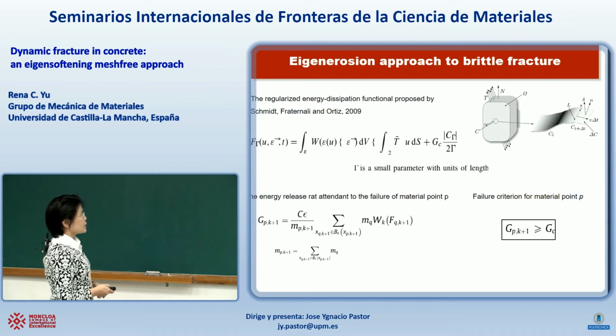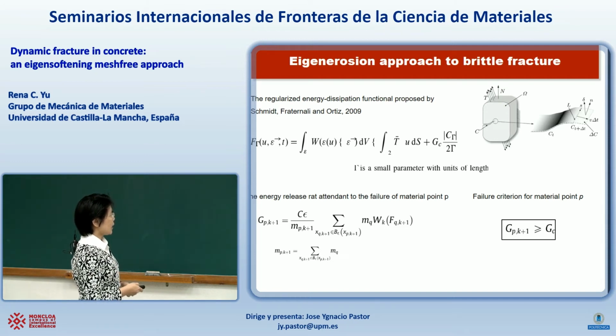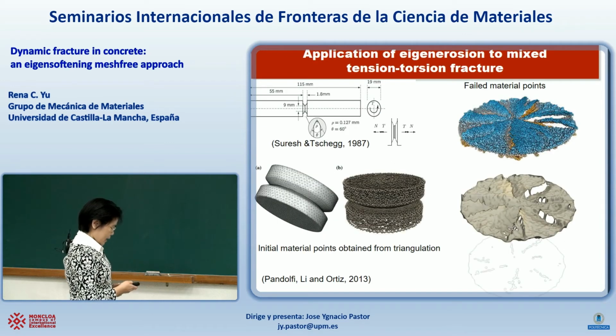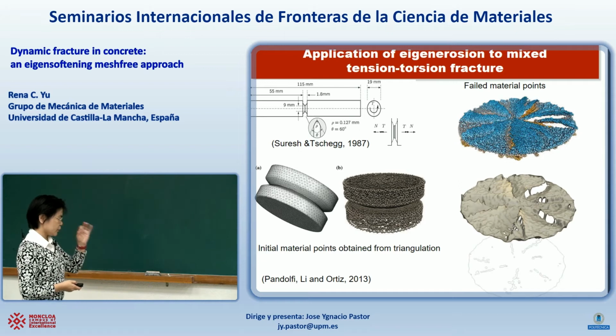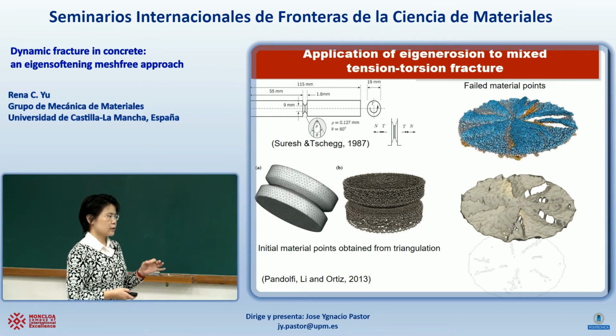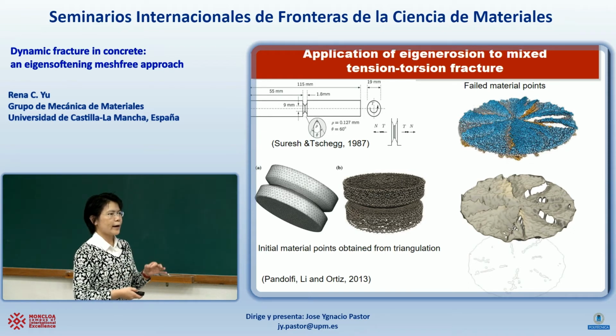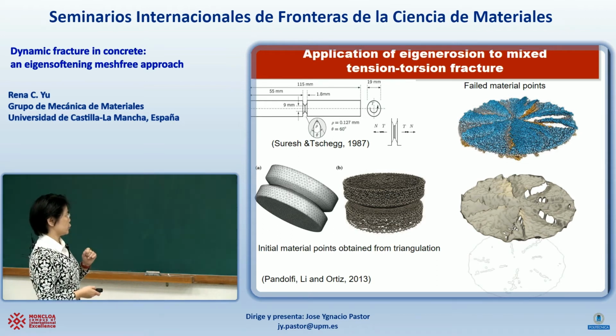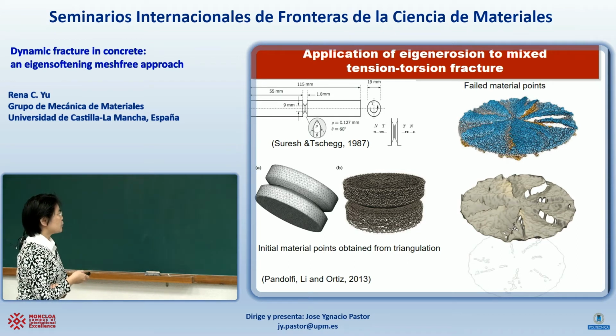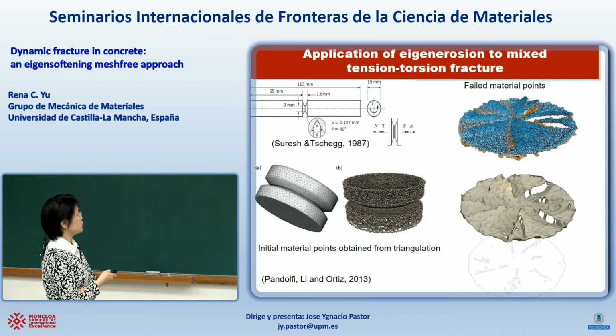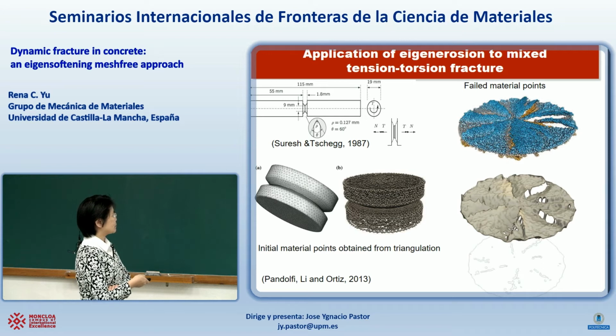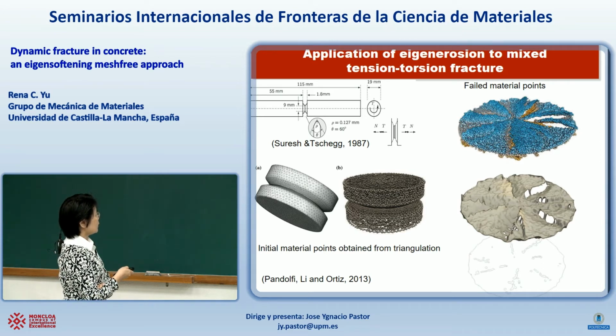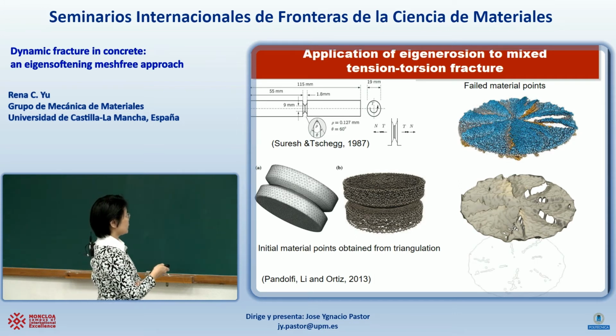And the criterion for fracture is that if this energy release rate is greater than the specific fracture energy of the material, then a crack is formed. And for the crack that forms, since there is a material point, the material point fails by the so-called erosion technique, so the material loses its entire stiffness. That's why the method was called eigenerosion. And this eigenerosion approach was designed for perfectly brittle materials, even though later on they have used it, for example, this is for metal, which is aluminum, to simulate the mixed tension torsion fracture that was carried out by Suresh and Tschegg in 1987.